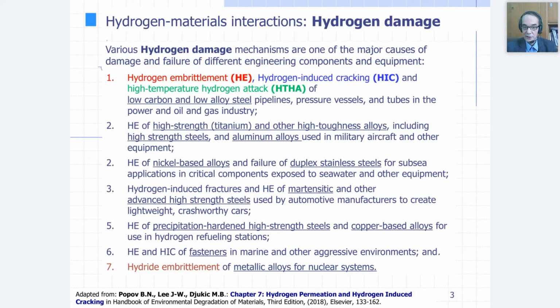As you can see, almost all structural materials are affected by hydrogen embrittlement and other hydrogen damage mechanisms, like low carbon and low alloy steels, also advanced high-strength steels, martensitic steels, and other grades of steels, but also aluminum alloys, also nickel-based alloys used in seawater and other equipment, and also copper-based alloys. But recently it is confirmed that high entropy alloys are also very susceptible to hydrogen embrittlement. So a lot of mechanisms and a lot of materials are prone to hydrogen embrittlement.